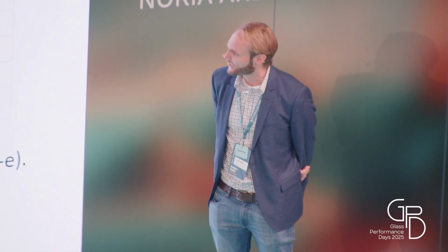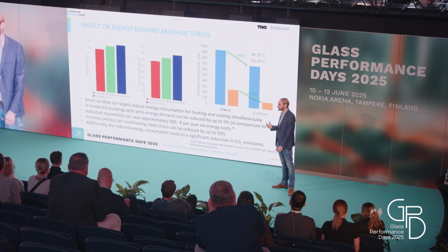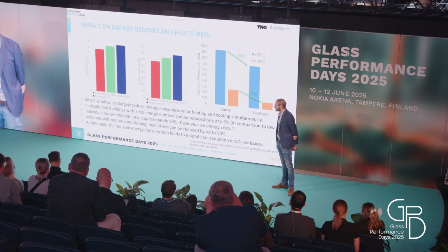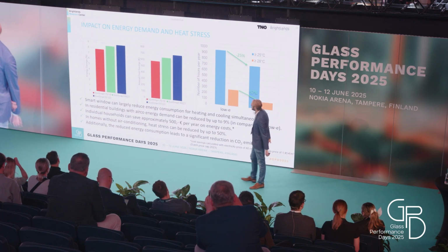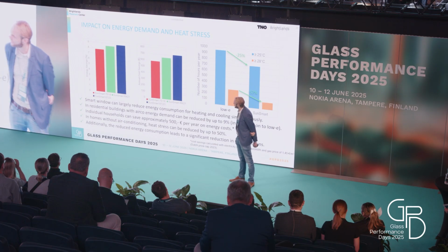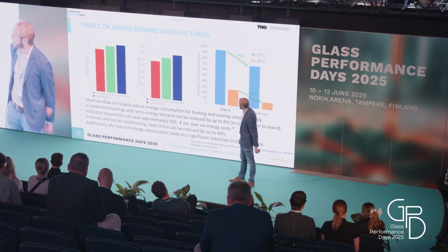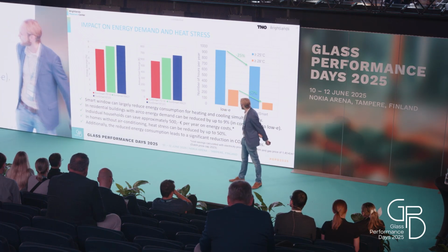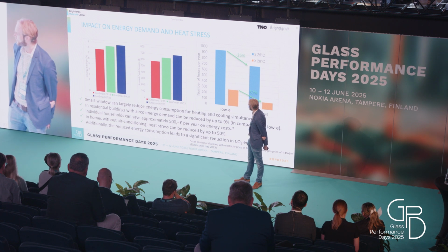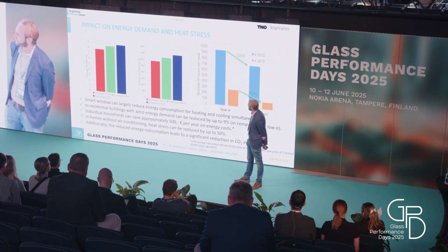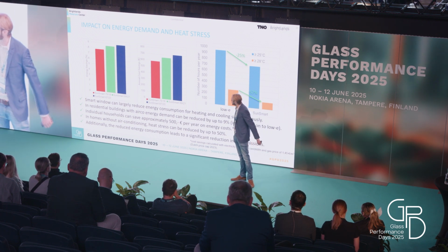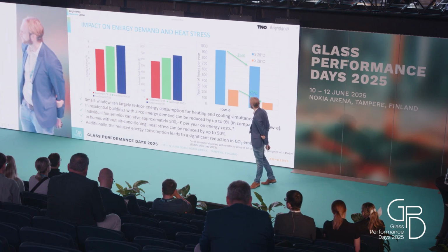Now you're thinking, okay, what is the impact of these kinds of smart windows on the energy efficiency and on comfort levels for humans? And here we did some building energy simulations where we compared the smart window to regular low-E coated windows. And here we can see that we can have large energy savings as a combination of reduced heating and cooling consumption in the Netherlands. And this can also lead to significant cost savings for homeowners.